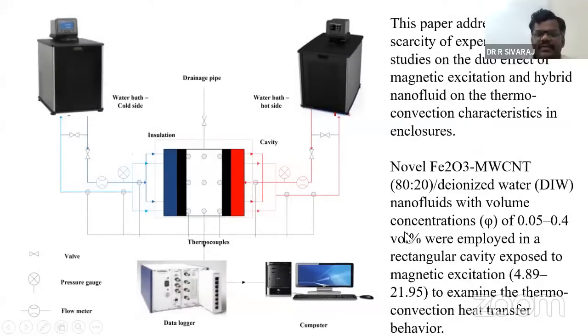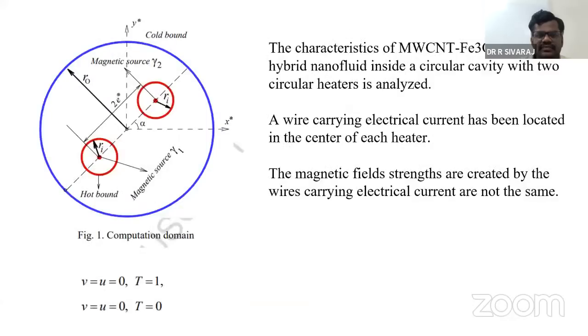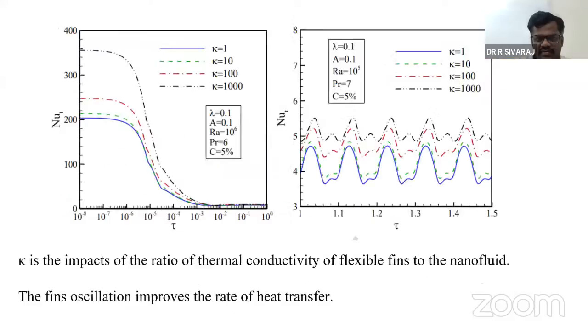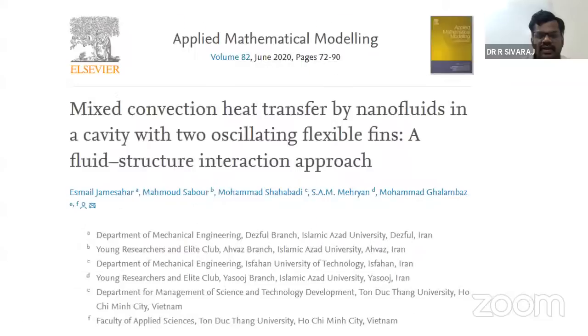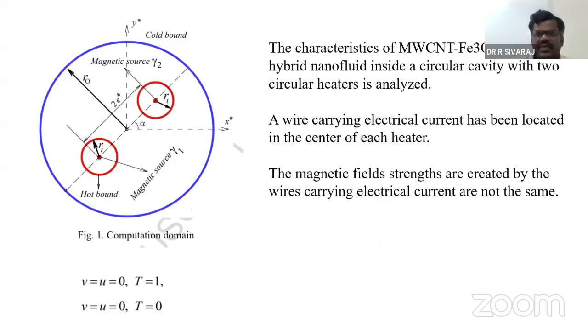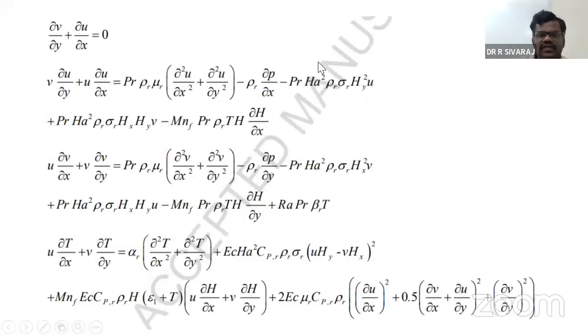In this, novel ferric oxide and multi-wall carbon nanotube based nanoparticles with an 80:20 ratio are suspended into deionized water. If you see this study and this study, in this study, theoretically, we have studied the water, ferric oxide, and multi-wall carbon nanotube based hybrid nanofluid. And the magnetic field we have generated through a wire, that is through this equation. So the magnetic field is being represented through this.